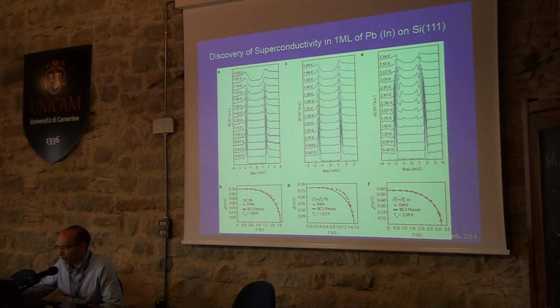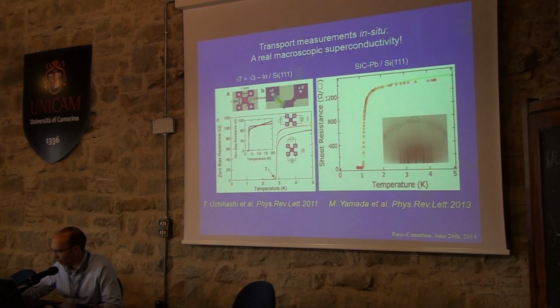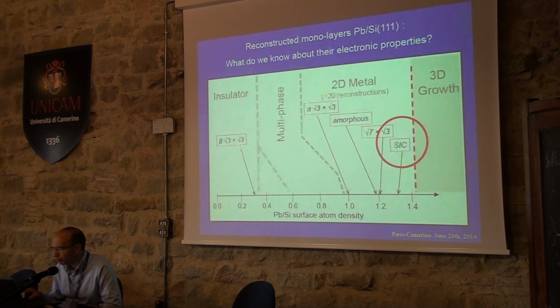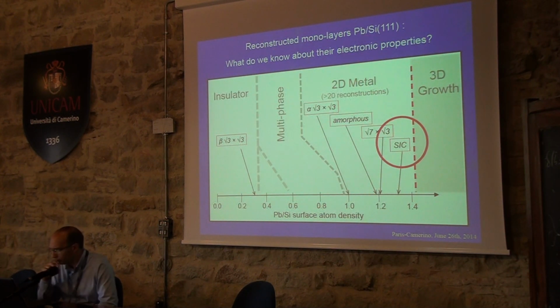There is a superconducting gap in this material. If you look at how this superconducting gap closes with temperature on the left bottom and central bottom plots, you understand that these materials are superconductors with a critical temperature of about 1.5 Kelvin. Next plot, please. And this superconductivity is real macroscopic superconductivity, in the sense that if you run transport measurements on macroscopic samples, you can really see the resistive transition towards a zero resistance state. Next slide. So now we focus on this striped incommensurate monolayer, which is superconducting below 1.6 Kelvin.